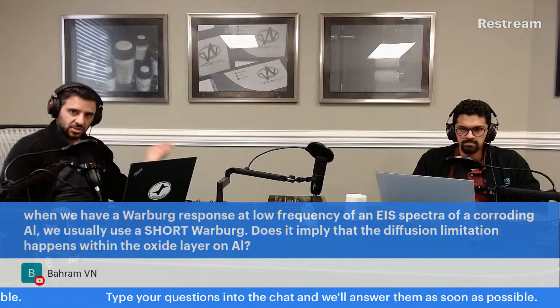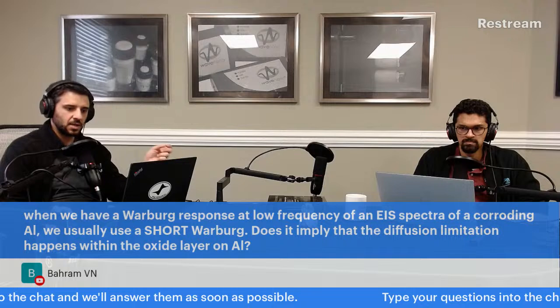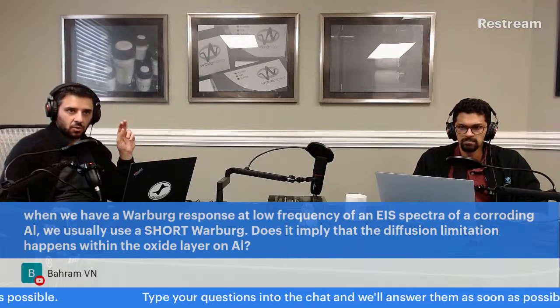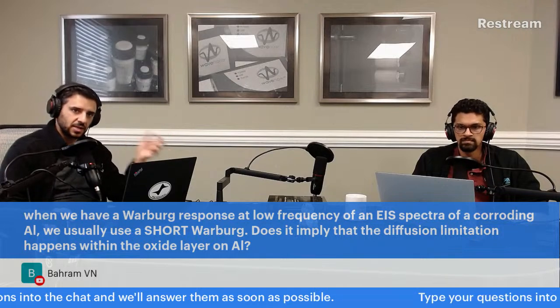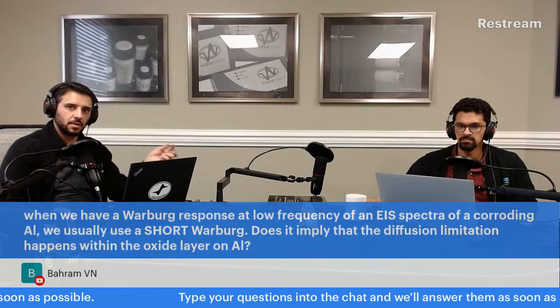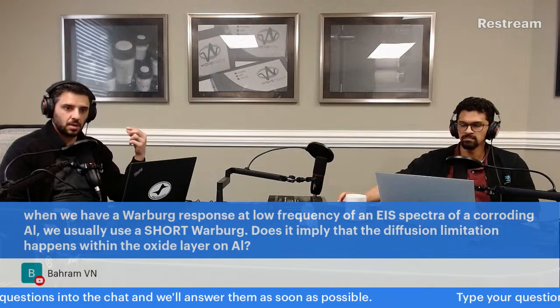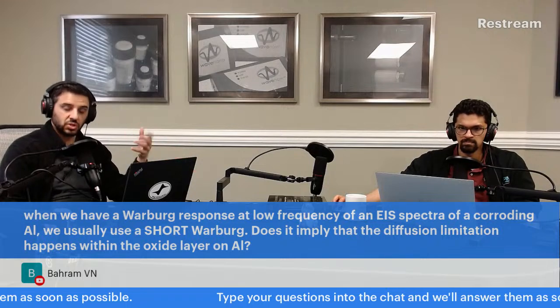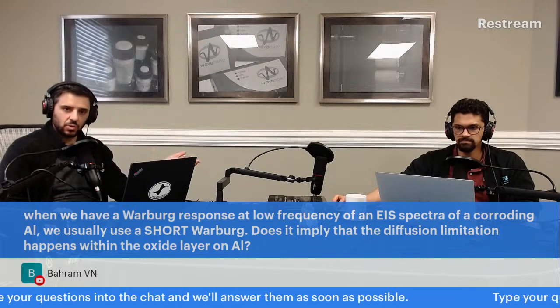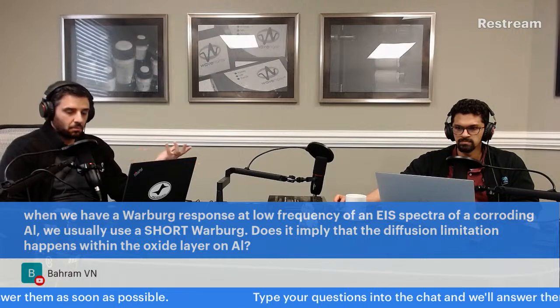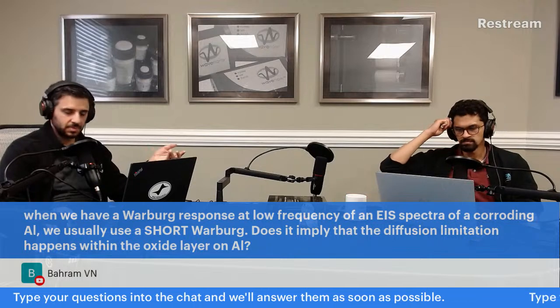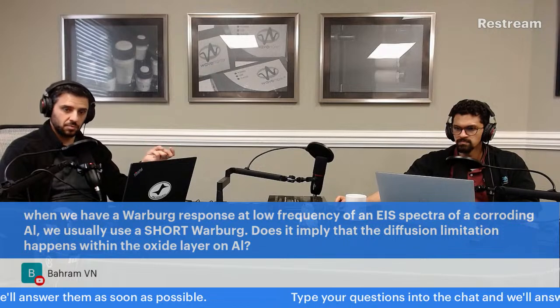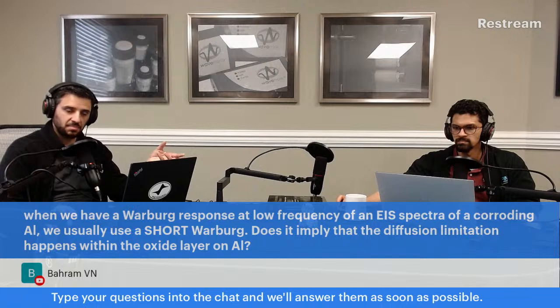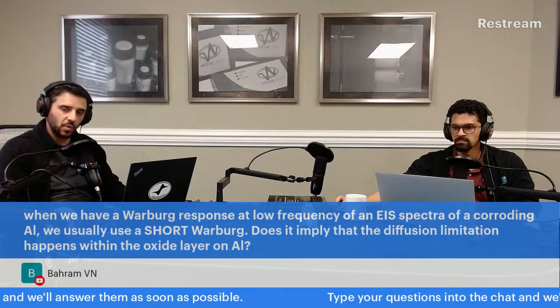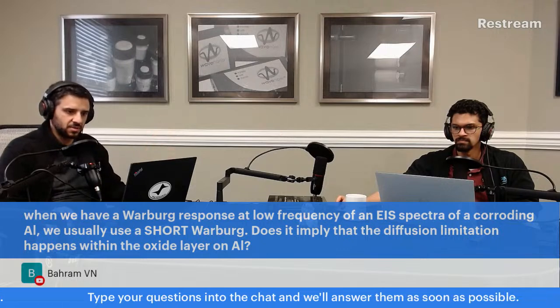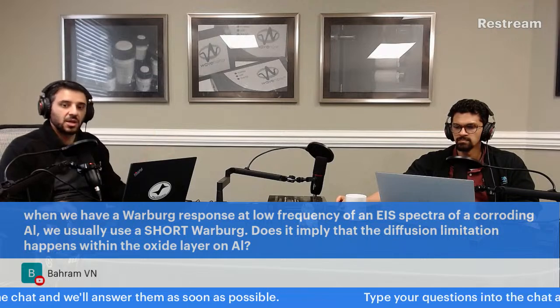And so, just as a suggestion, if you suspect this is the corrosion taking place in the oxide layer, extract from your circuit fit and calculate as best you can a measure of the diffusion layer thickness from the Warburg short circuit fit. And then if you have some sort of physical, spectroscopic, microscopic technique, SEM, some kind of spectroscopy where you can probe the surface to get a physical measurement of the oxide layer thickness, maybe that's not possible. So this might not exactly be easy, but if there is a way for you, or in the literature, for instance, if you find someone who did determine the average thickness of your oxide layer, you could compare the two, is my point.